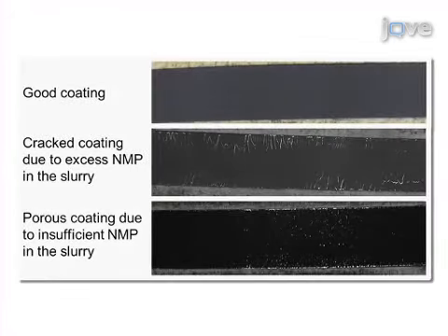In the preparation of the working electrode, it is important to create a slurry of good consistency. These results compare good and bad coatings after drying. Note, a cracked coating typically results from a slurry that has excess NMP, and a porous coating typically results from a slurry that has insufficient NMP.